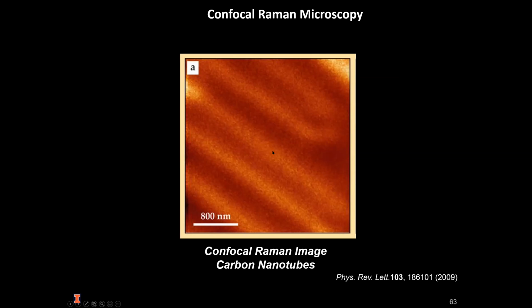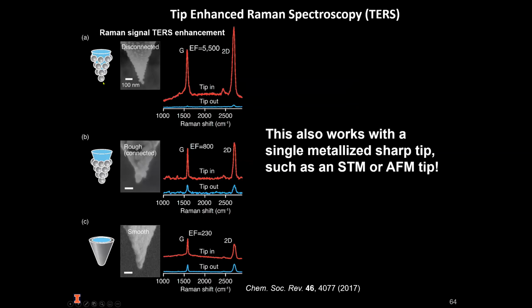And it just happens that the same scheme that we use for surface enhanced Raman spectroscopy can also be realized by a single sharp metal tip, such as an AFM tip or an STM tip. So not only do you get the electric field enhancement, but now the source of the Raman signal is extremely localized.